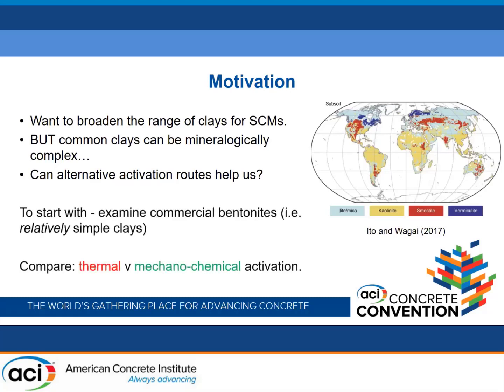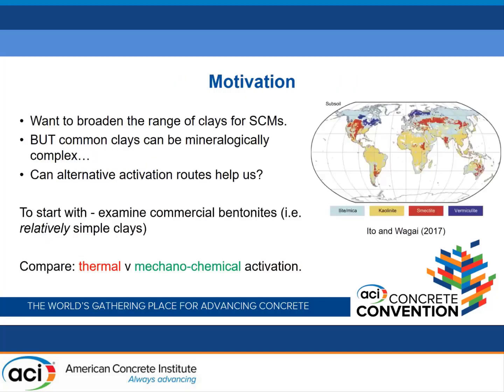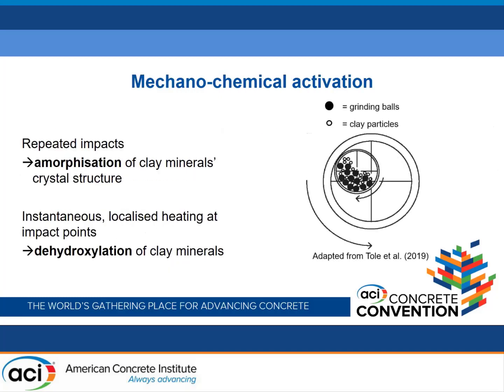In this study, we did a comparison of thermal and mechanochemical activation for two commercial bentonites, which is a relatively simple starting point to quite a big and complex question. In case anyone is not familiar with the concept of mechanochemical activation, you can simply describe it like this: through repeated physical impacts, we get both amorphisation of the clay mineral's crystal structure as well as dehydroxylation — the same effects that we get from thermal treatment, albeit through physical means. The most common way to achieve this is planetary ball milling, and that was what we used in this study.